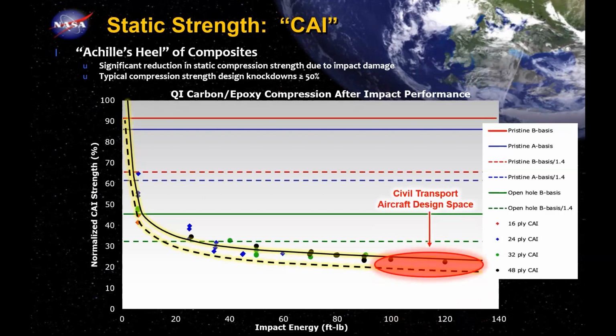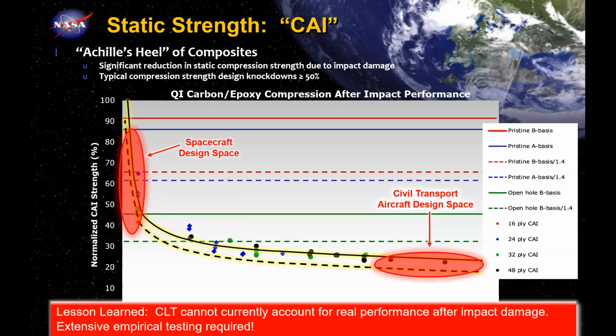And if now I look at where that crosses over on my regression curve fit value, I'm less than, say, 10 foot-pounds, and I'm in trouble. And so you can see the two circles there. Civil transport aviation, for airplanes that you fly in on a common basis, they're designed for the kind of damage you see there way over on the right. And the good news is they're on the flat of the damage tolerance strength curve. And that's a good thing, because if they miss the amount of energy that they might be designing to, plus or minus, hopefully that structure doesn't fall apart. Unfortunately, for spacecraft, we're way over here on the left, on the steep part of the curve, and this is where it gets difficult. Next slide.